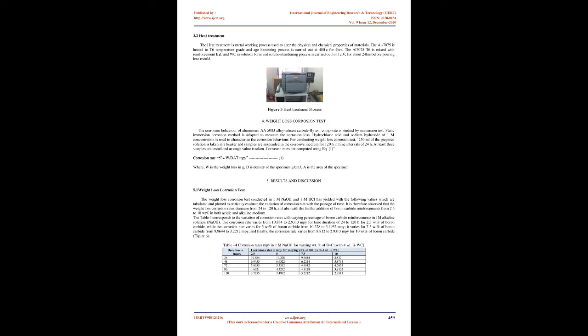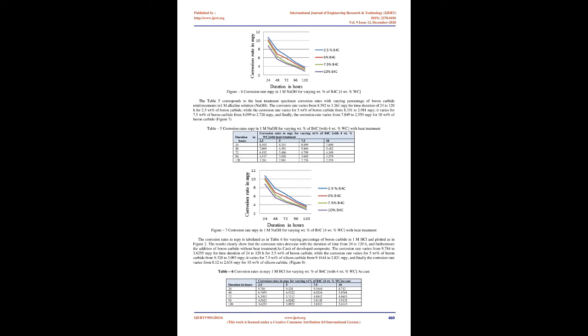4. Weight loss corrosion test. The corrosion behavior of aluminium AA5083 alloy silicon carbide fly ash composite is studied by immersion test. Static immersion corrosion method is adopted to measure the corrosion loss. Hydrochloric acid and sodium hydroxide of 1 M concentration are used to characterize the corrosion behavior. For conducting the weight loss corrosion test, 250 ml of the prepared solution is taken in a beaker and samples are suspended in the corrosive medium for 120 h in time intervals of 24 h. At least 3 samples are tested and the average value is taken. Corrosion rates are computed using Eq. 1, where W is the weight loss in g, D is the density of the specimen in g/cm3, A is the area of the specimen.